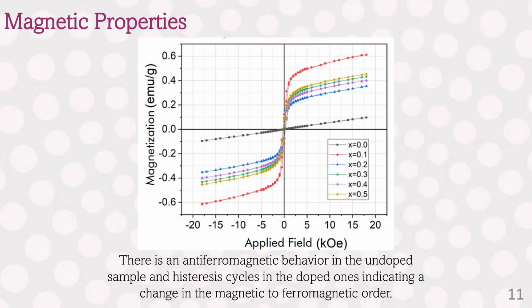The LFO, as mentioned above, crystallizes in a G-type AFM structure, which tells us that by the spatial arrangement of the Fe3+ spins, with intrinsic angular momentum orientation, result in opposite spin orientations, so that their magnetic moments cancel each other. Now, the magnetic behavior is a consequence of the superexchange interactions between the Fe3+ and O2- bonds, so modifications of the structure will have direct repercussions on the magnetic order of the ferrite.